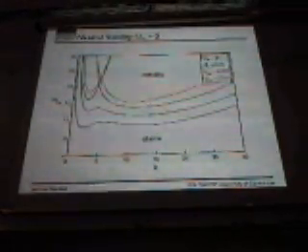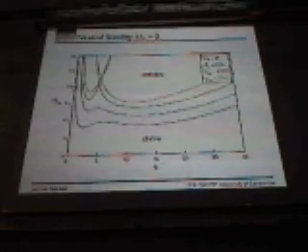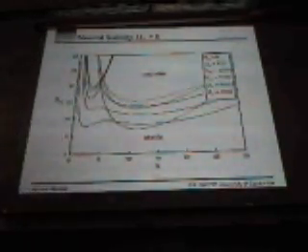If we take an external flow of varying strength past one of these mushy layers and conduct the same sort of linear stability analysis, we can make a plot again of the Rayleigh number versus the wave number, and we see that initially it stabilizes both these boundary layer and mushy layer modes of convection. But as the flow is increased to yet higher velocities, you can start to destabilize first the boundary layer mode and then the mushy layer mode.